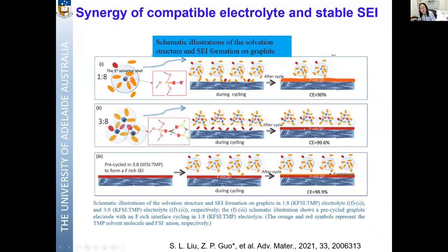So we form a fluoride-rich SEI, this SEI is quite dense and uniform, and therefore can achieve very good potassium plating stripping reversibility with coulombic efficiency about 99.6%. But at low concentration, although the solvent is still fire retardant TMP, because there's some free molecule there, it may form a phosphorus-based SEI. This SEI is not as dense as the fluoride-rich one.